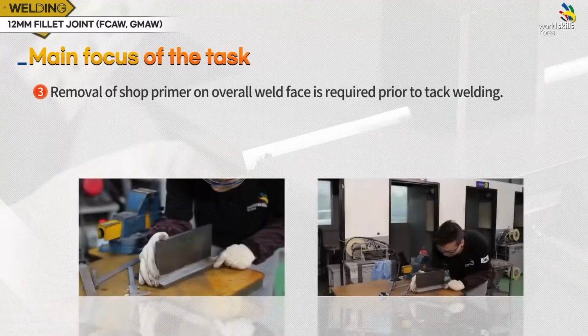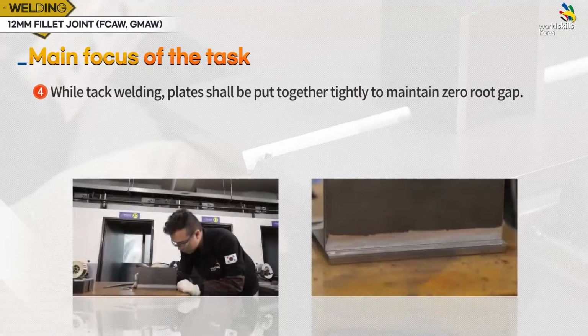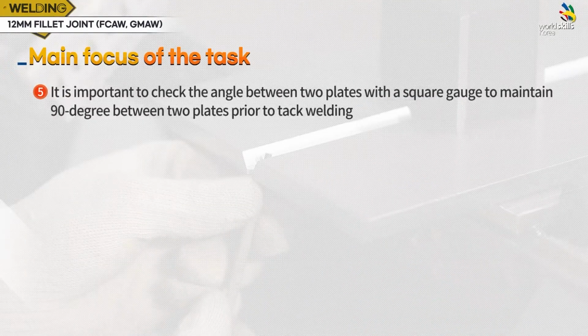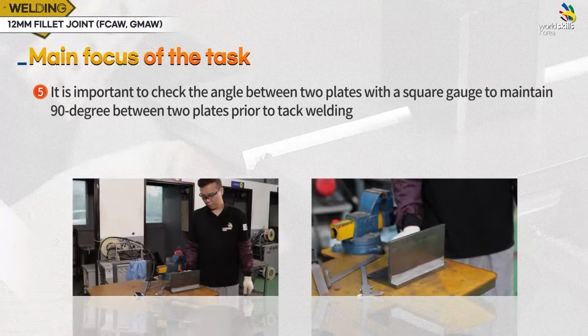Removal of shop primer on overall weld face is required prior to tack welding. While tack welding, plates shall be put together tightly to maintain zero root gap. It is important to check the angle between two plates with a square gauge to maintain 90 degrees between two plates prior to tack welding.